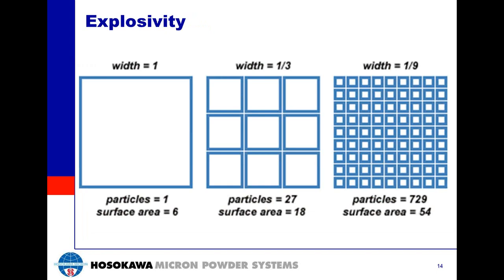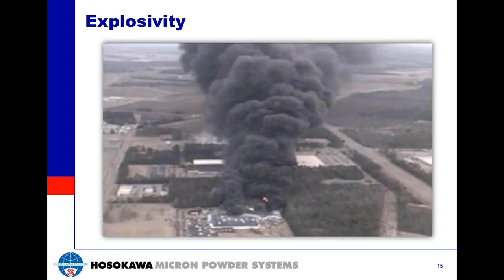Another physical danger is explosivity. The smaller the particle size, the greater the surface area, and with some materials, the greater the surface area, the more explosive it can be. Equipment in your factory may be able to handle finer particles, but might not be designed to handle their explosivity. If you over-grind your product and do not analyze the particle size, or you receive an incorrect particle size result, these materials have the potential to explode, causing catastrophic damage to equipment, the facility, major injuries to operators, and in some cases, death.